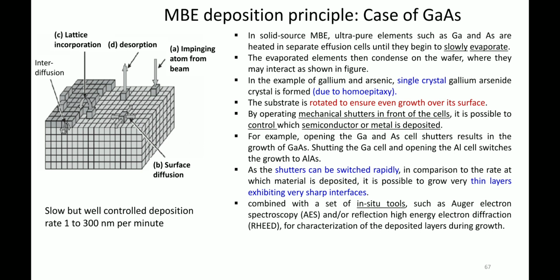I have to close the shutter for gallium, I have to open the shutter for aluminum. Okay, so when I open the shutter for aluminum, then the aluminum arsenide starts to grow. So likewise, you can make multilayers of different composition. As the shutters can be switched rapidly in comparison to the rate at which material is deposited, it is possible to grow very thin layers exhibiting very sharp interfaces.